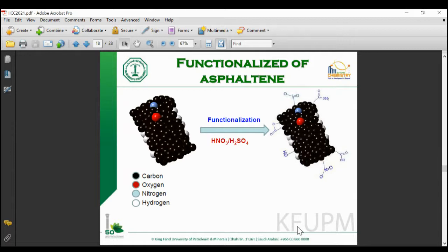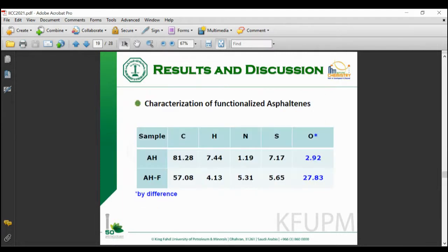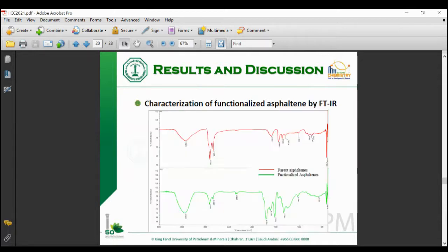Okay, this is a model just trying to show you that this asphaltene, we did the functionalization using nitric acid and H2SO4, and it develops the oxygen moieties, carbonyl groups, and others. When you look at the elemental analysis, initially it was 2.92% oxygen. After functionalization it is 27.83%, which is also supported by the IR. You can see the development of the IR bands at the carbonyl region that indicates that the asphaltene now bore the carbonyl groups and maybe the ether linkage.